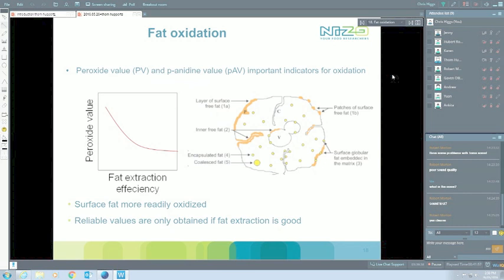Very important there when you look at milk powder, but you can also relate that to, for instance, infant formula and other products, is that fat on the surface is free, is readily accessible for any residual oxygen that is in the packaging, and that is what will oxidize quite quickly and easily and can start leading to off flavors. And you can even relate that back the other way. Of course, typical ways of looking at fat oxidation is, for instance, a peroxide value that people like to measure. And what you tend to see is if your fat extraction efficiency is poor, so in cases where you only really take the surface fat out of it, you measure very high peroxide values, and you basically give an unrealistic picture of a complete product.